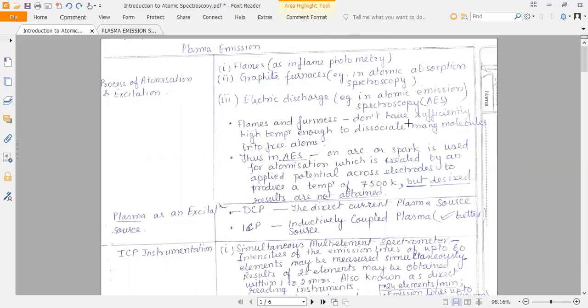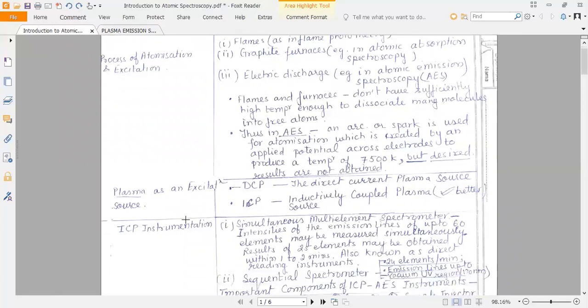Flames and furnaces don't have temperatures high enough to dissociate many molecules into free atoms. Thus, in AES, an arc or spark is used for atomization, which is created by an applied potential across the electrodes to produce temperatures of 7500 kelvins, but desired results are not obtained. When we use plasma as an excitation source, which are of two types, direct current plasma and ICP, we get the desired temperatures, and out of these two, ICP is the better source.